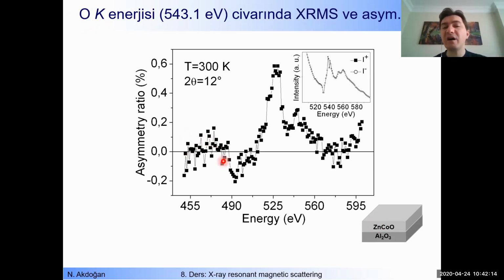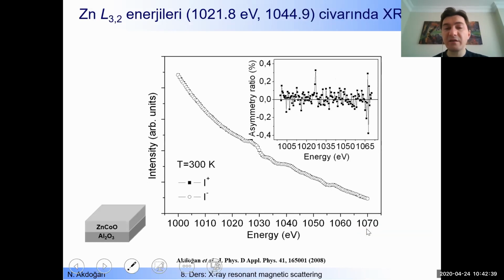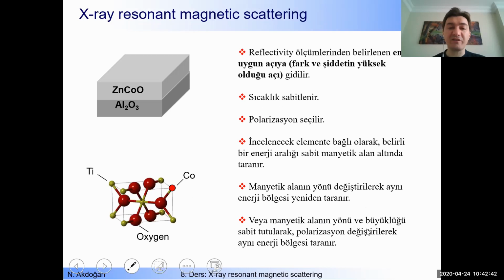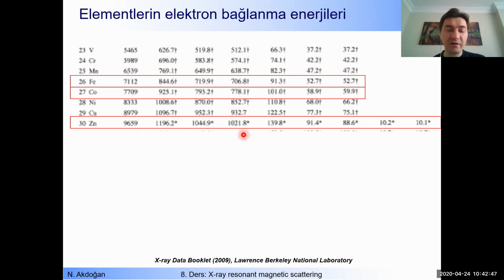So this is very nice and very useful data. You cannot get this data by using other methods. So we can clearly show that the cobalt sits on the zinc oxide lattice and makes bonding with the neighboring oxygen atom. So now let's also try to investigate the zinc. What about the zinc energy? Zinc energies are around here, more than 1 kilo-electron-volt.